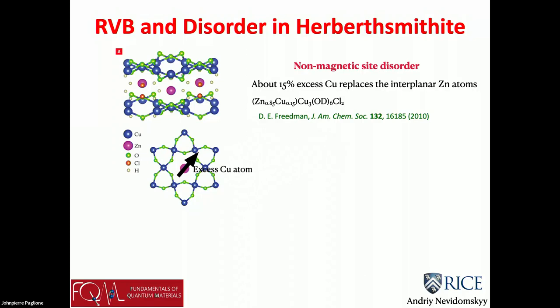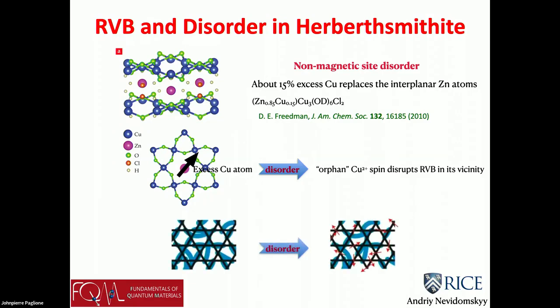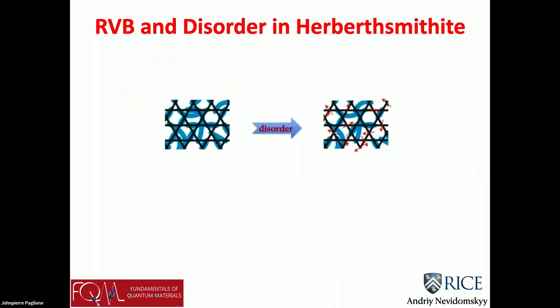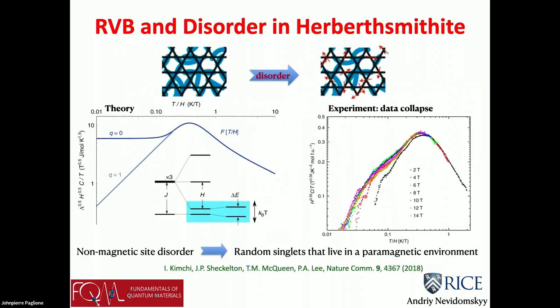You stick it in between the planes, and all these extra spins polarize the blue spins that sit above and below. And so this creates disorder, because you don't do it on every hexagon, you do it on average one every seven or so. And this disorder ends up creating a bunch of moments and destroys your quantum spin liquid. So this has plagued the field for a long time. There's a bunch of both theoretical and experimental data. For instance, shown here is a beautiful data collapse.